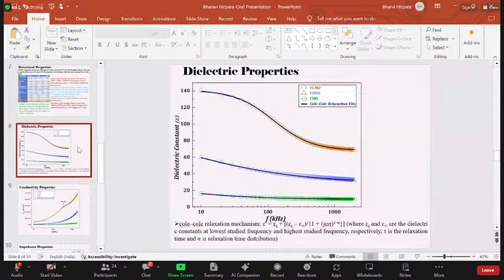Here we have seen the variation in dielectric constant with frequency. There is a reduction in dielectric constant for all the samples as frequency increases, and we can ascribe this to the field induced enhancement in dipole relaxation. That is, the response of dipoles becomes weak at higher frequencies, which leads to suppression in the capacitance of the material. Also, we can see here that the dielectric constant of YMO is found to be lower, because of the presence of A-site disorder within the lattices of doped manganese due to ionic size mismatch between yttrium and divalent dopant ions.